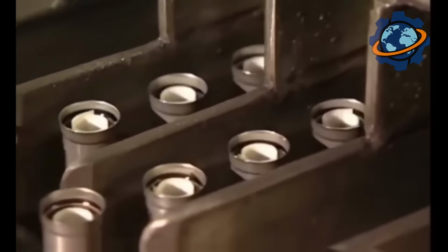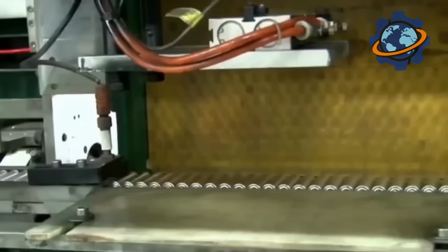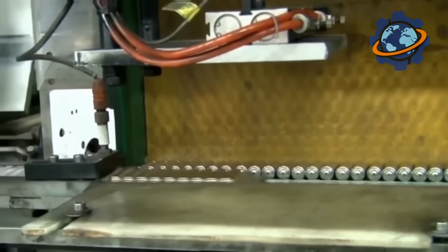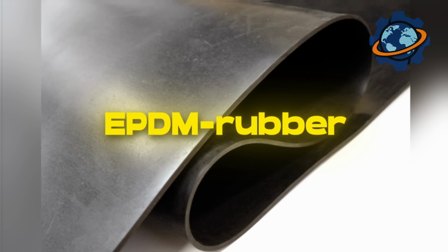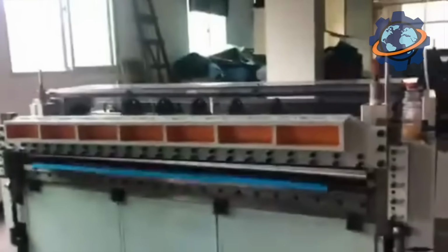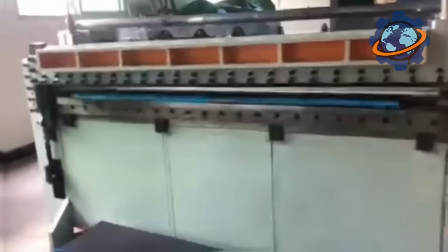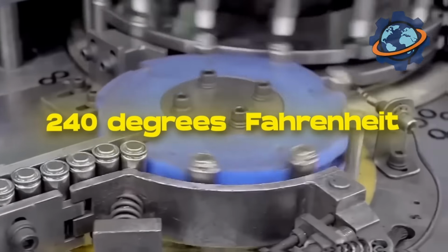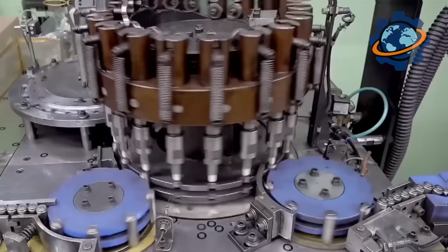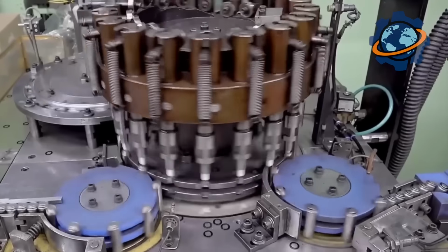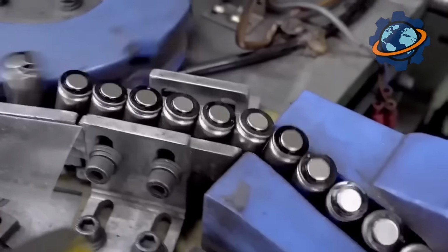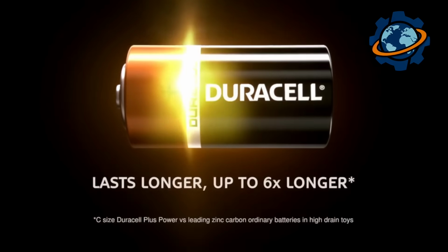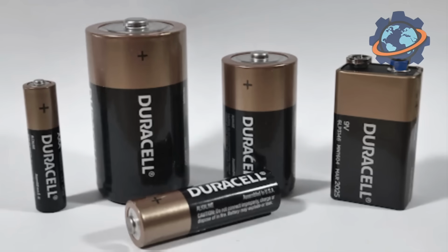It must be sealed. The cell is closed with a sealing gasket and a metal disc. Here, sealing washers made of EPDM rubber are used. This is a type of synthetic rubber that does not let the electrolyte through and can withstand temperatures up to 230 degrees Fahrenheit. The gasket is inserted with micron precision because even a small misalignment and the battery will lose pressure, and with it, its life.